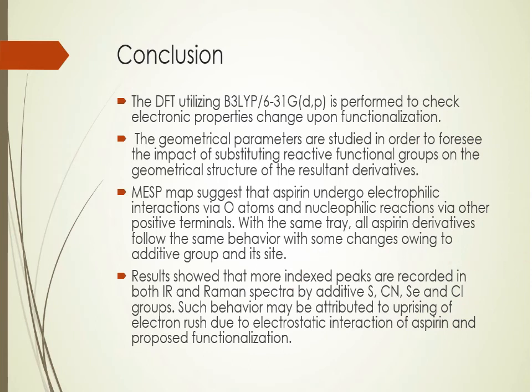Conclusion. The DFT utilizing B3LYP was performed to check the electronic properties change upon functionalization. The geometrical parameters were studied in order to assess the impact of substituting reactive functional groups on the geometrical structure of the resultant derivatives. MESP maps suggest that aspirin undergoes electrophilic interactions via oxygen atoms and nucleophilic reactions via other positive terminals. With the same trait, all aspirin derivatives follow the same behavior with some changes owing to the additive group and its site. Results showed that more indexed peaks are recorded in both IR and Raman spectra by the additive sulfur, cyanide, selenium, and chloride groups. Such behavior may be attributed to an uprising of electron rush due to electrostatic interaction of aspirin and the proposed functionalization.